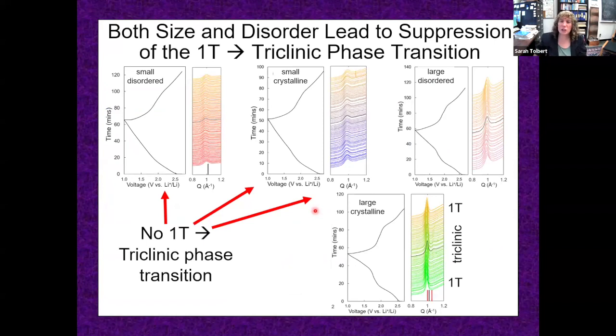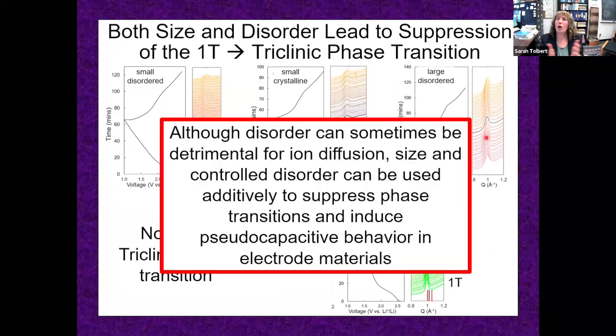We can do that X-ray diffraction experiment, and what we see is only the biggest, most crystalline samples have phase transitions. Both size and disorder can suppress those phase transitions. And so overall, what our take home is, you might say disorder, isn't that bad for lithium moving through a material? But both size and disorder can be used additively to suppress phase transitions and turn battery materials into fast charging pseudocapacitors.